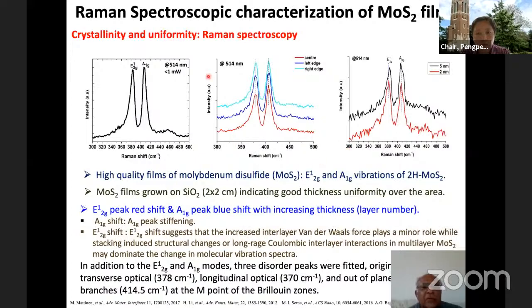Now going back to using the Raman spectroscopy technique for characterizing the crystallinity of the film and the uniformity of the film. Here are the three slides. You can see here the Raman spectroscopy technique is used for characterizing just one layer, a very thin film. And then we maintain the thickness and make a larger area film, and we have characterized at different spots under the same condition. And we find the film appears to be relatively uniform.